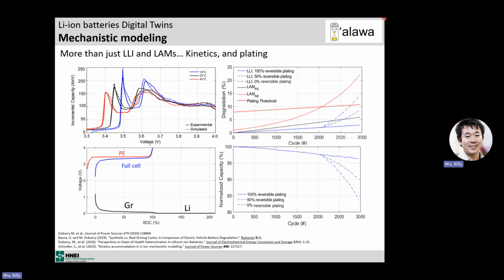But we can play on that, the model, right? We can select any amount of loss of lithium we want. So we can, as a parameter, set the reversibility of plating. And that allows us to simulate paths like that one with reversible plating, and paths like this one where the plating is not reversible, and we can predict that acceleration. So that knee, we can predict it from the start, because we can predict the rate of loss of negative, we can predict the rate of loss of lithium, and we can set the reversibility. So the knee, predict it. That's one of the possibilities for knees, but with that model, we can predict it.